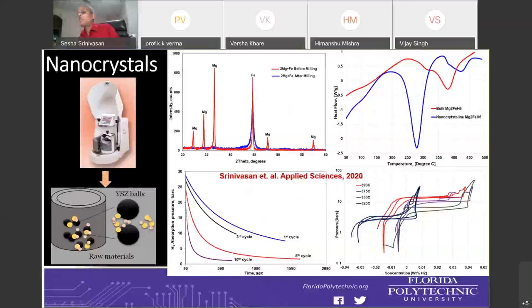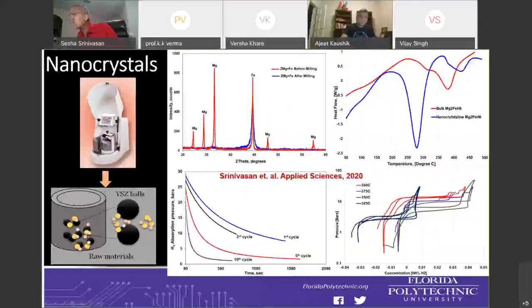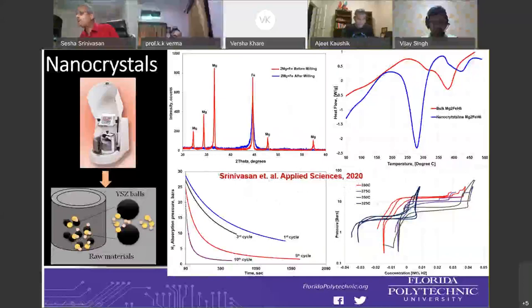I can also use ball milling in a planetary ball milling system, where I can reduce the particle size, and the full width at half maximum is increasing, so that I can produce a nanocrystalline version, which was published in 2020, Applied Sciences. That shows the kinetics and the thermodynamics of these systems: you can see the temperature reduction from bulk, about 400 degrees, all the way to 300 degrees C by using the nanocrystalline version of the materials.